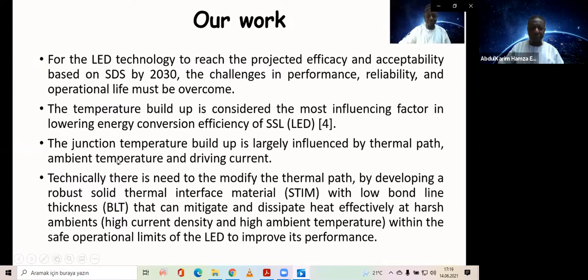And then the ambient temperature within which the LED is operating, and then higher driving current. Technically, there is a need to modify the thermal path by developing a robust solid thermal interface material with low bond line thickness that can mitigate and dissipate heat effectively at harsh ambient, that is a combination of high current density and high ambient temperature within the safe operational limit of the LED to improve its performance.